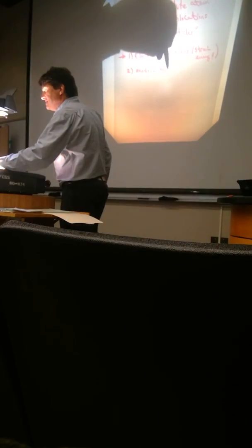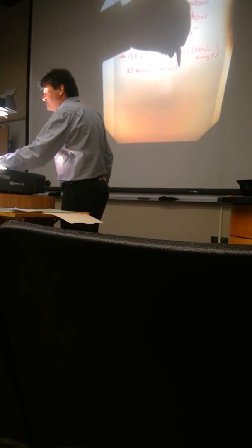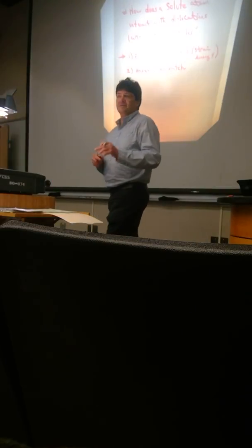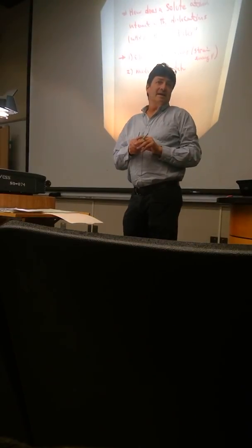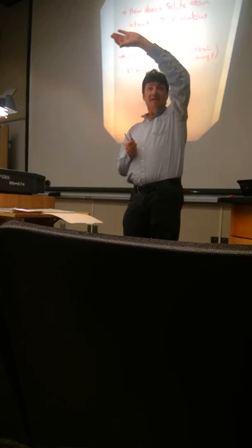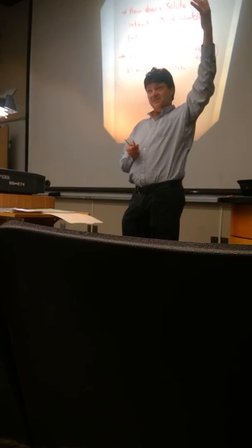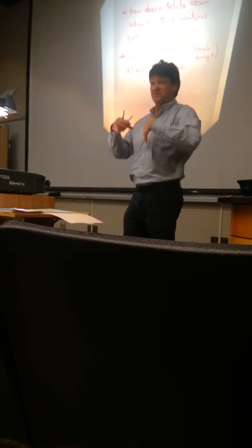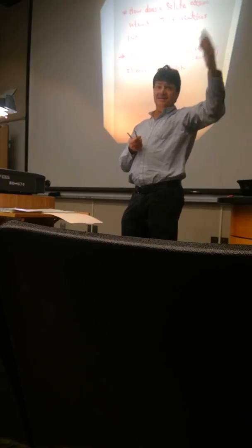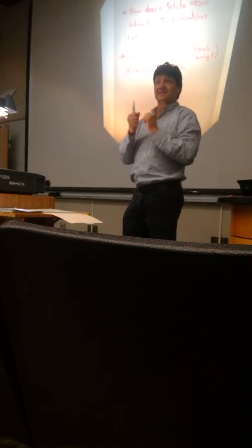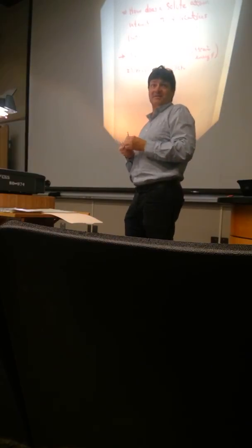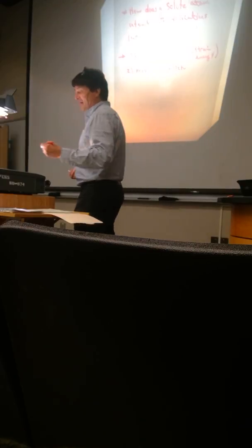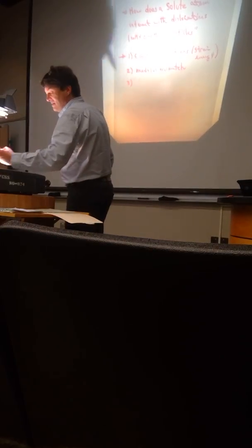Modulus mismatch. Remember, the tau is related to GB. G is the modulus of the material. If you add impurities that have a higher modulus, you're making it a little bit stiffer, and therefore your dislocation would have a higher energy. So modulus mismatch can do that.